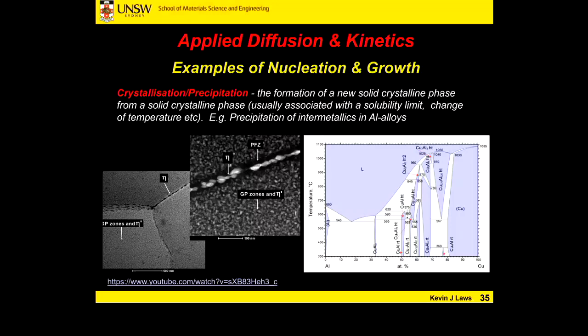What we notice straight away is there is a large concentration and an orientation relationship between the grain boundaries and these particles. So again, this is similar to that example that we saw with ice, but in reverse. At the grain boundaries, the structural energy is higher, and this can act as a favourable nucleation site for a new phase to form. That's what's going on here.